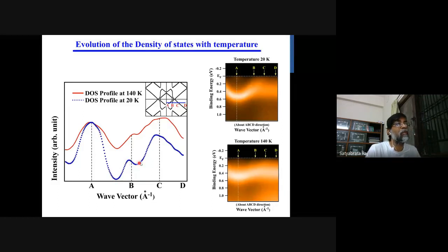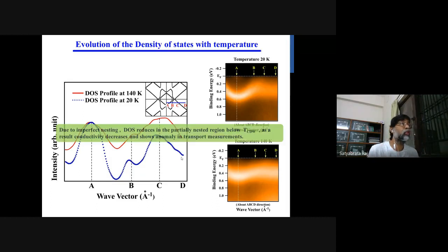whereas at low temperature you have a very much reduced density of states. This shows that, due to the partial, imperfect nesting, the density of states reduces in the partially nested region below the CDW temperature. As a result, conductivity decreases and shows an anomaly in the transport measurements.